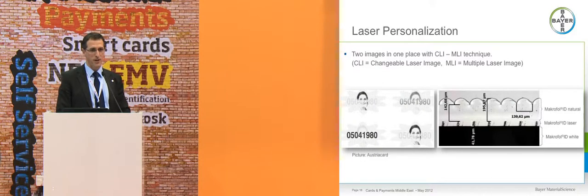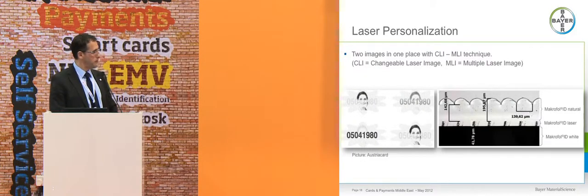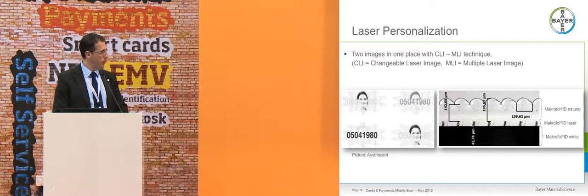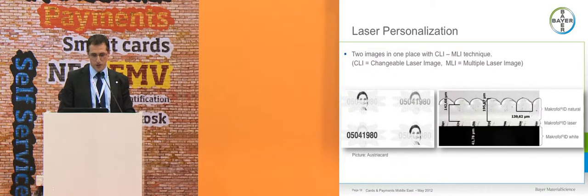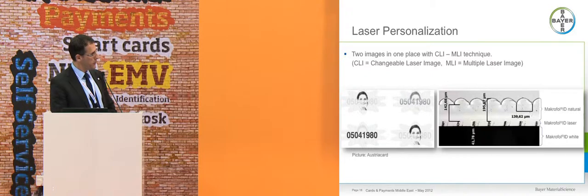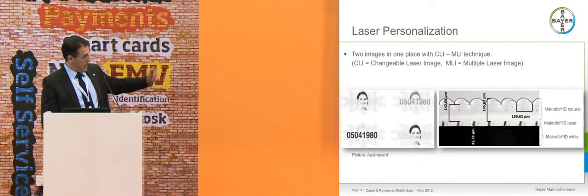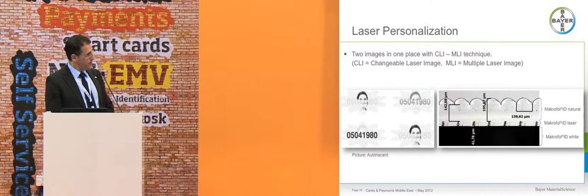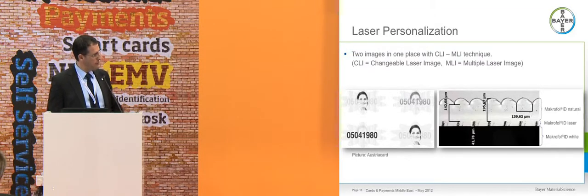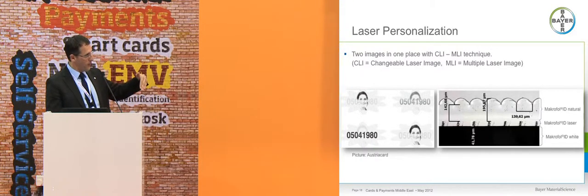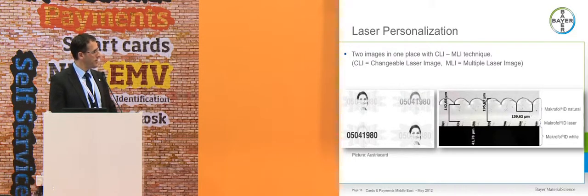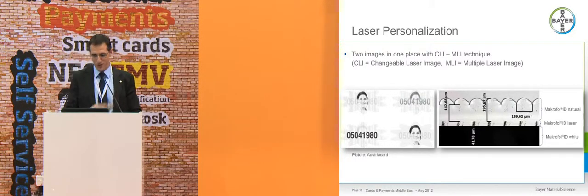Also CLI and MLI features are very comfortable to be done with polycarbonate films. You see here in this picture a profile cut through a card made with an MLI security feature. You see the part of transparent material on top and the laser engravable part of the film beneath it. And by doing that and then accurate focusing of the laser, you can get that multi-picture laser engraving images in there.